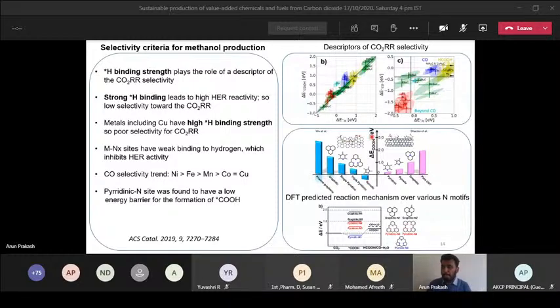So whenever you have a minimum energy, it is better. So the materials containing pyrrolic nitrogen sites are performing better than the pristine ones without the nitrogen site, and this applies to the graphitic and pyridinic ones. If it is applied to a graphitic carbon, it is graphitic nitrogen. So different types of nitrogen you can tune. As I told, you can see here graphitic nitrogen, pyridinic nitrogen, depending on the number of rings. Okay.